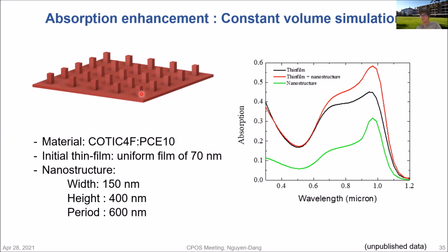This structure consists of pillars with 150 nanometer width and 400 nanometer height and a period of 600 nanometers. And you can see that with the thin film, we have this kind of absorption. Now, if we add the nanostructure on top, then we can really enhance the absorption out of the visible without changing the absorption in the visible.